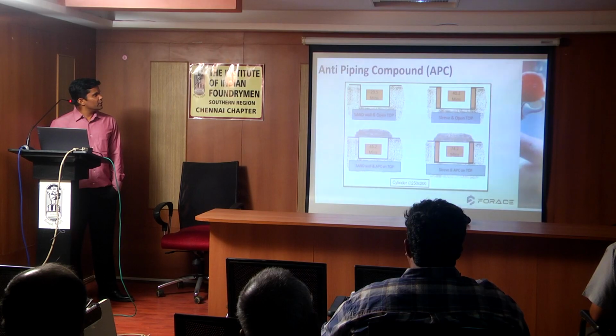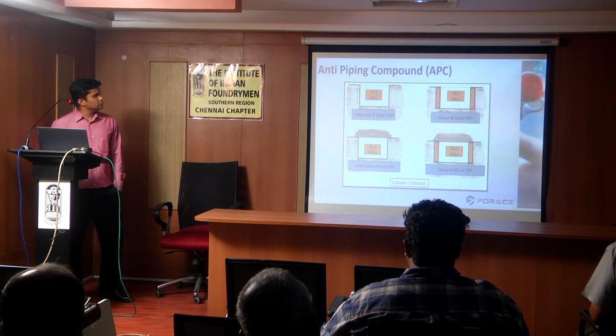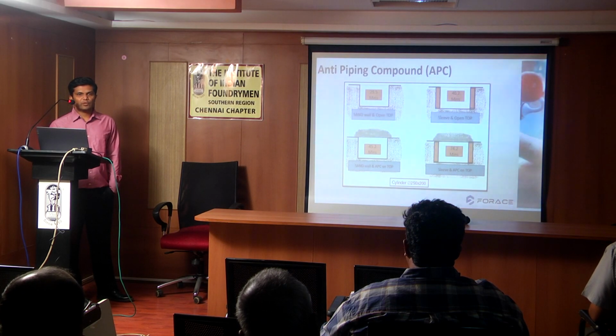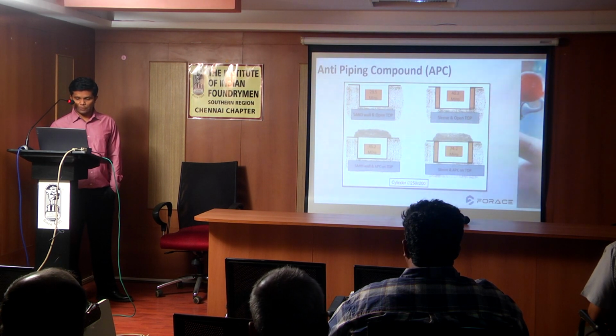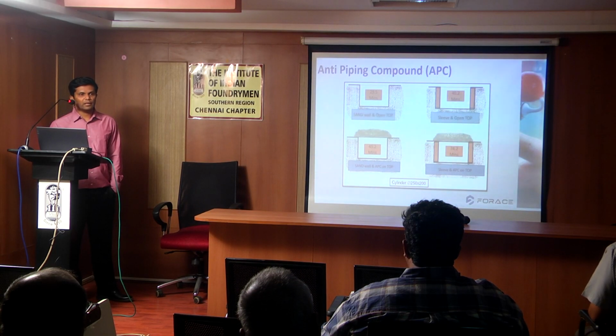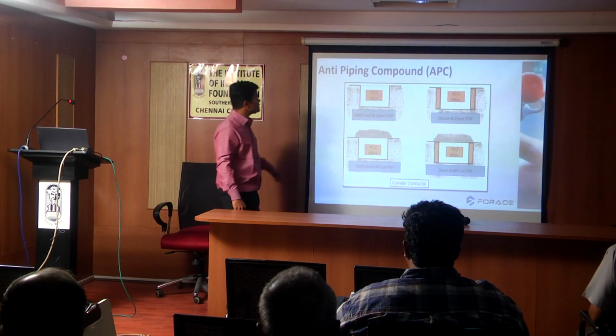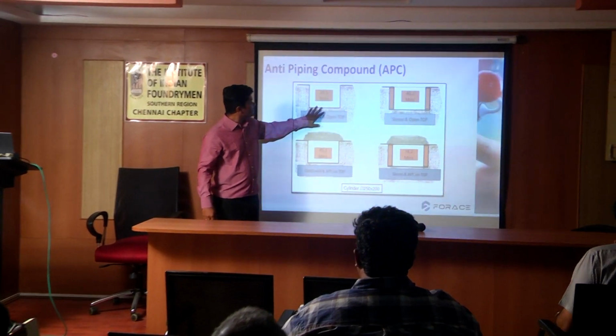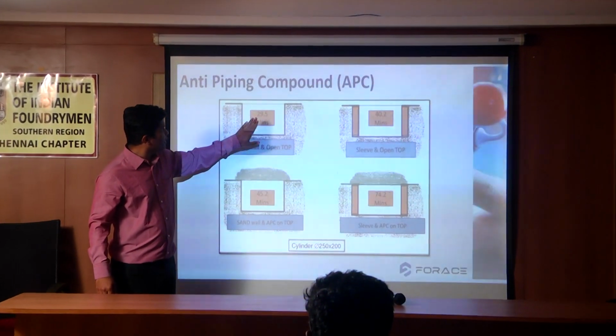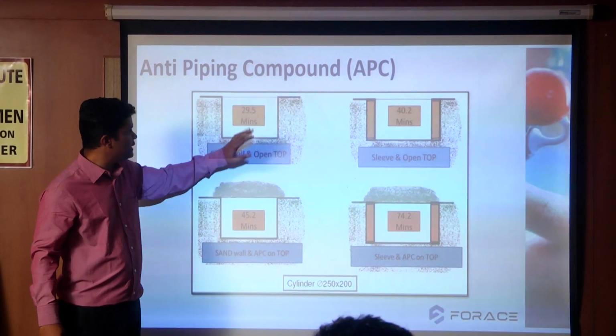This is the working principle of the anti-piping compound. Maximum heat transfer will be from the top area. So if it is an open riser, you can put an anti-piping product to restrict that heat loss, so that the riser will remain in a molten condition for a longer time. So this is just an example: if it is an open sand riser, then it is solidifying in 30 minutes.